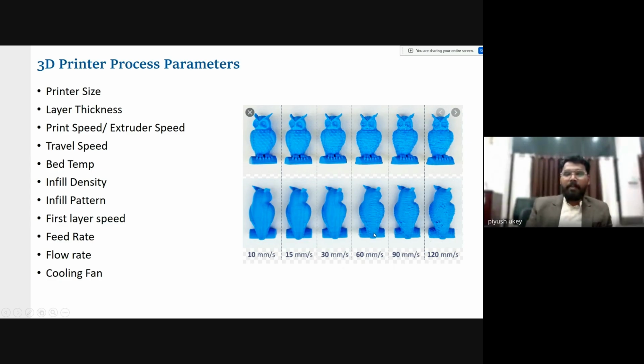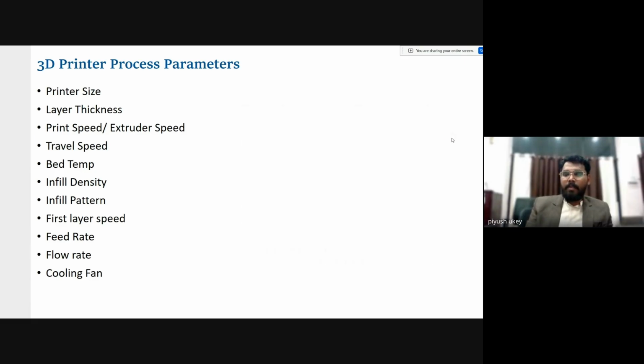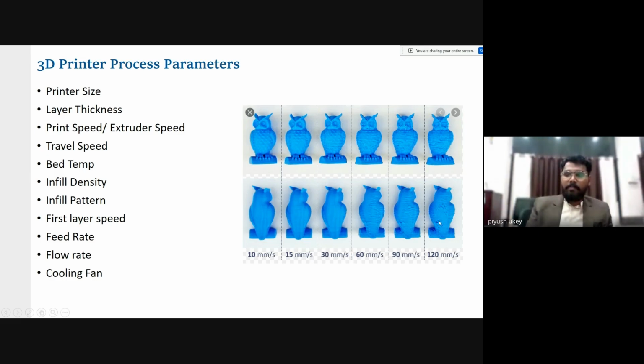As you can see, as the print speed is increasing gradually, the surface finish of the printed part has been reduced drastically. With the slowest printing, almost all the features have been preserved, and it shows a very high quality and detailed print. But with 120 mm per second of print speed, we can see almost all the details have been lost, and even some voids have been generated. So the print speed also needs to be optimum.